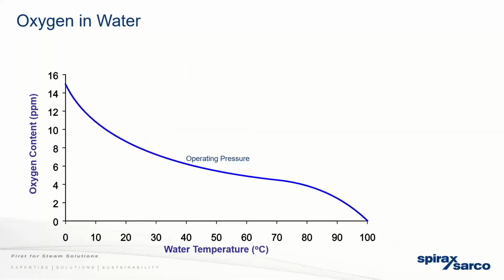You can look at this one up here at varying temperatures. You can actually see how the ppm of oxygen will change. The lower the temperature, the higher the content of oxygen. So oxygen in water is directly correlated with the temperature itself. If you're looking at heating up the water, that's when you can get rid of oxygen. The higher it goes, as you can see, if it goes to 100 C, it goes to 0, because if you're boiling the water, you're getting rid of air at the same time. But in the deaerator, you're not technically boiling the water, but we'll get to that as well.